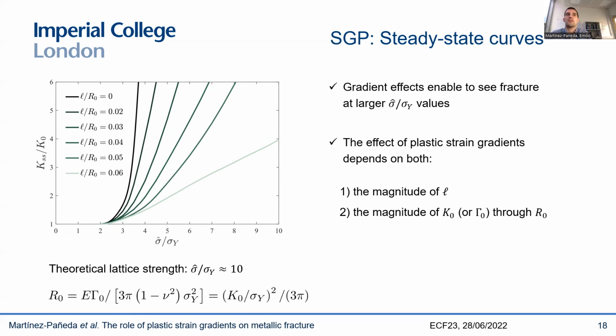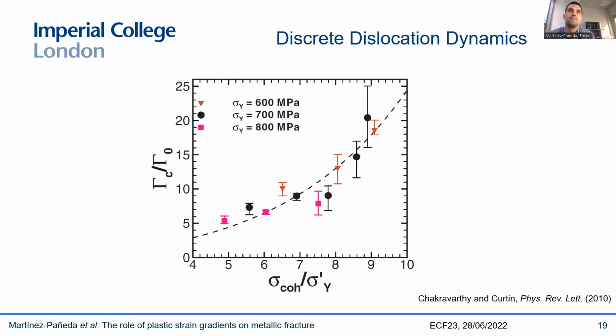And this is what is happening essentially, right? You can have a lot of plastic work coming out of those dislocation densities, the evolution of those dislocations, but you can still get very high stresses if your fracture region is small compared to the ability of the material to harden due to the presence of GNDs. And again, I emphasize that the length scale is a material parameter, but R0 is dependent on the fracture energy, so it depends on the fracture micromechanisms that are taking place. And what is interesting is that, in fact, if you look at discrete dislocation dynamics, and this is taken from Bill Curtin's group, you can see that this is actually what they predict.